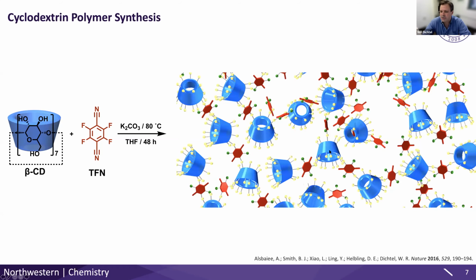If you shrank yourself down and could see this at the molecular level, it might look something like this, where we've got all of these different cups linked by these TFN crosslinkers. Because the whole system is rigid, with rigid cups and rigid TFN itself, these things can't really fill space perfectly well. They get restricted, and so you enforce having some voids in this network, and that permanent porosity gives rise to the material having a high surface area. It allows the pollutants to reach each cup quickly, and that's a key part of the design as well. That's really what made this material special over other attempts to make polymers that contain cyclodextrin for water purification.